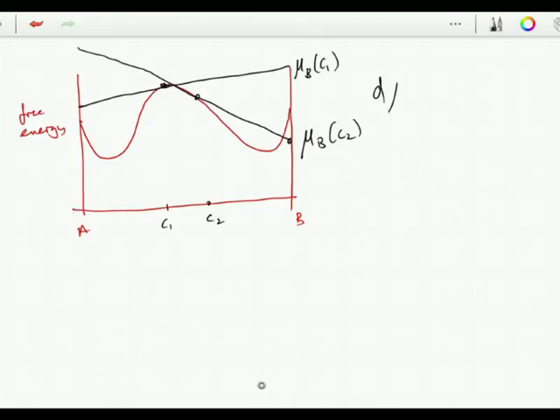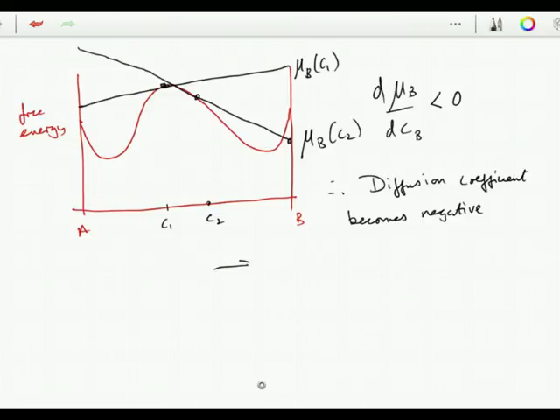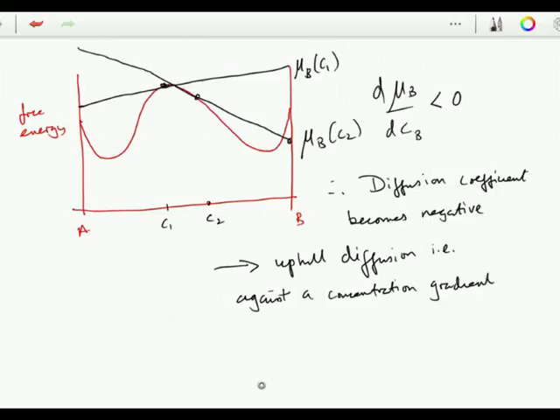we have d mu B by dC B is less than zero, and therefore the diffusion coefficient becomes negative, and this gives us uphill diffusion, that is, against a concentration gradient. So a homogeneous solution will tend to develop A-rich and B-rich clusters given time for diffusion to occur.